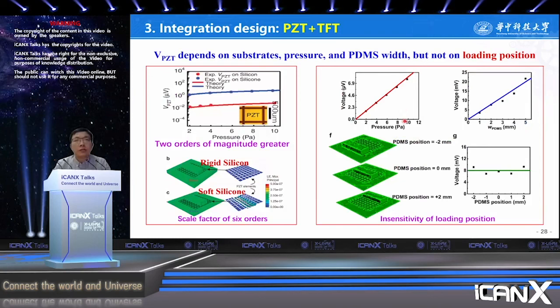Firstly, the piezoelectric response is critical for the pressure sensor. The dependence of the voltage of the PZT on applied pressure is different for PZT sensors on a rigid silicon wafer and on a soft silicone substrate. This one is rigid silicon, this one is soft silicone. The PZT device on the soft substrate offers a response more than 2 orders of magnitude greater than that of the identical device on the silicon wafer. So the softer the substrate, the bigger the output.